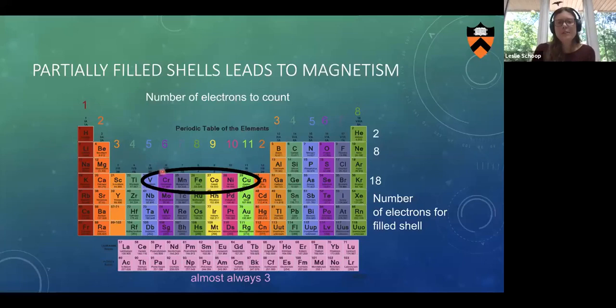This is related to the electronegativity difference that we just discussed. If you have, for example, chromium chloride, a famous magnet now, you have a large electronegativity difference and we will more likely have magnetism. So you can get a rule with these elements up here, like oxygen, fluorine, chlorine, sulfur, nitrogen to some extent: it's very likely with a 3d transition metal element to get magnetism. With oxygen and fluorine, even with these more down below here. But if you have chromium together with aluminum, maybe I'm not 100% sure to have a good example now, there are some intermetallic phases that are not magnetic. So don't be disappointed if you make a new cobalt phase, like cobalt aluminum, and you just have a non-magnetic metal. That's totally possible.